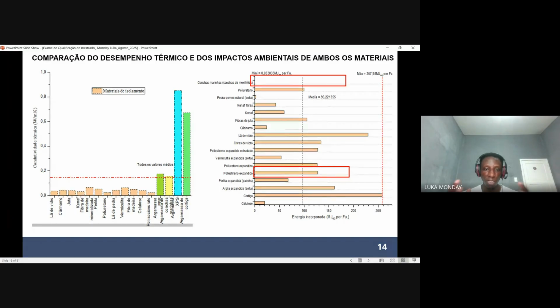And the aim of this is to recycle this material to achieve similar properties to the traditional insulation materials. On the aspect of embodied energy, utilizing the embodied energy of 1 meter squared on the production of all these materials, and comparing them with the traditional insulation materials, it is clearly seen that seashell has a lower embodied energy compared to any other material. However, studies have shown that the production stage of this material consumes a lot of energy. Even with a lot of energy, it still has a lower embodied energy compared to the rest of the materials.